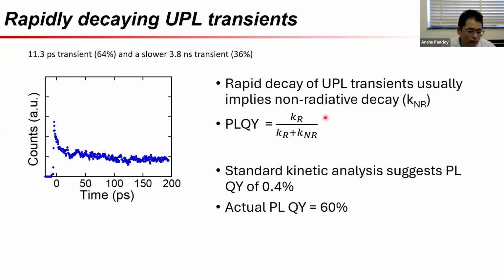This is part of undergraduate learning, where you would actually use it. You would say that, okay, I have kinetics at play here. So I have a radiative kinetic. I have a denominator which is made up of radiative and non-radiative rates. And this ratio of these two rates, the sum of these two rates and this thing, is my luminescence quantum yield. Great. So if we actually use TCSPC to get an estimate of KR, and then we divide by KR plus